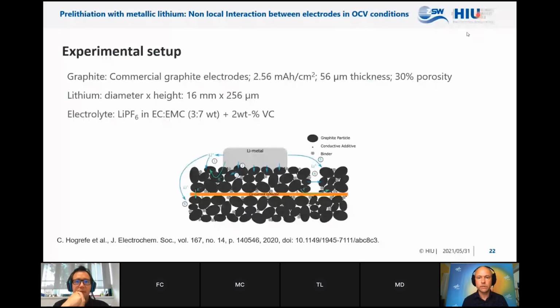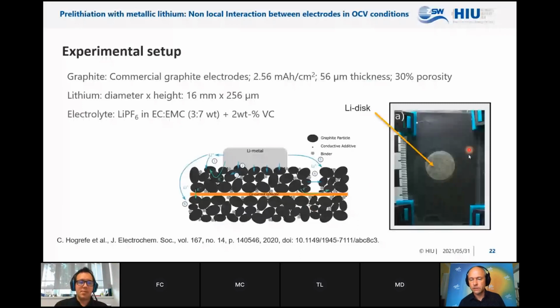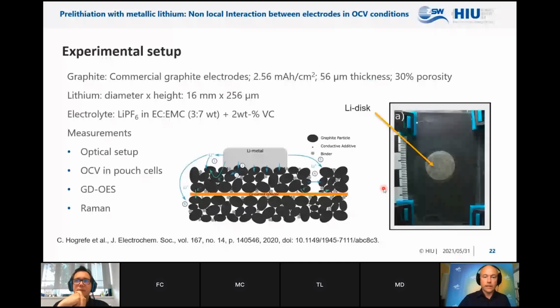Here are the experimental conditions. So this is how the experiment looked like. Here's the lithium, this is the graphite electrode. And then they observed the full system just under OCV conditions. So there was no external current flowing, just OCV in a pouch cell. And they observed this with different experimental techniques: glow discharge optical emission spectroscopy, GDOES, and Raman. And we simulated the whole situation.